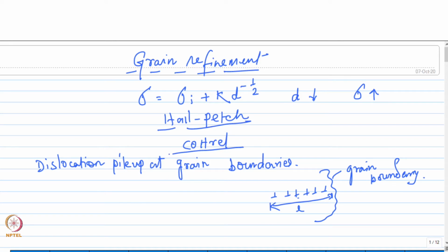From this, you can actually derive this Hall-Petch relationship based upon the stress which is developed at the tip of the pile-up. Okay, so that's what we did in the previous class based upon that stress tau s and a critical stress which is needed for the dislocations to move over to the next grain, tau c. We actually derived this Hall-Petch relationship. Okay, but there are certain limitations of this pile-up theory, because as we have seen, this is based upon the stress which is developed by the dislocation pile-up. So you need a large enough pile-up for that to occur.